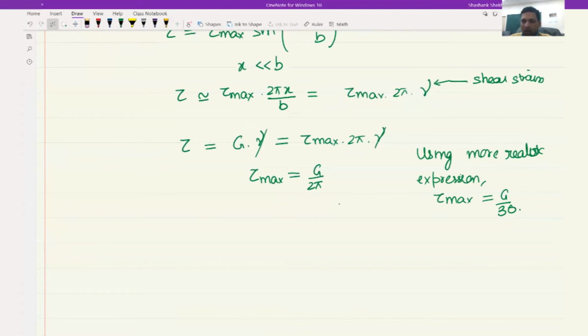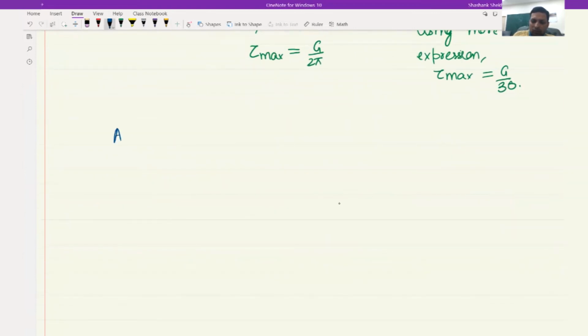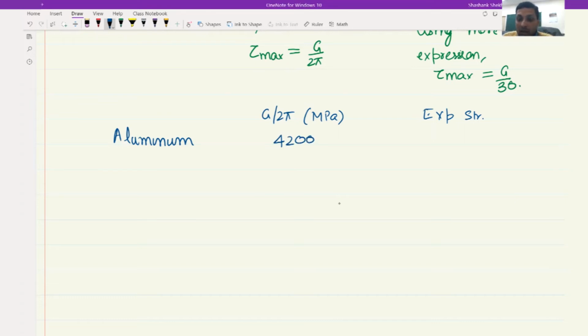Now let's compare it with how does it compare with experimental values. So for example, aluminum, here let's write G by 2 pi in megapascal and experimental strength. So the G by 2 pi for aluminum should be 4200 megapascal, meaning this is the amount of stress that you need to apply for the material to plastically deform, or somewhere close to this. This should be the yield strength of the material. On the other hand, what is the yield strength that we obtain for a single crystal?